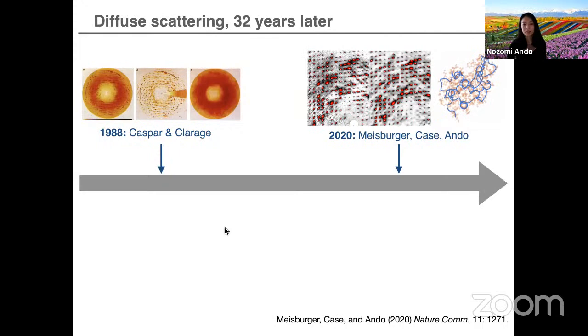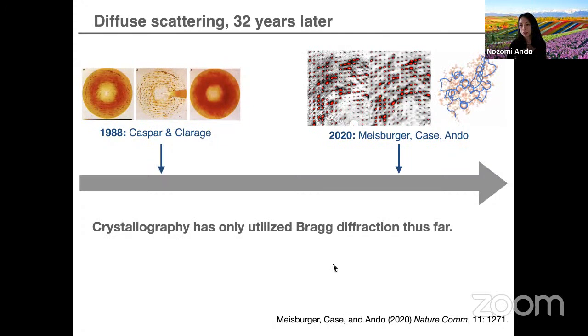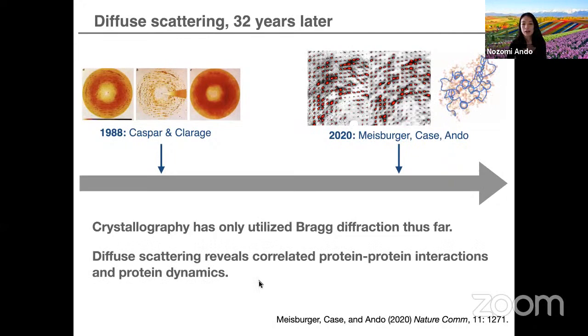Because of that, crystallography has really only utilized Bragg diffraction so far, but there are these two data sets. What we showed is that if we are very careful about accounting for all of the scattering, then there are two types of correlated motions that the diffuse scattering will tell us about. And I think they're both biochemically important. One has to do with lattice dynamics, but really they're telling us about long-range correlations due to protein-protein interactions. And then the other weaker signal, but still important signal, is the protein dynamics.